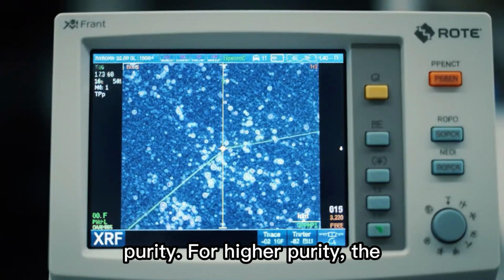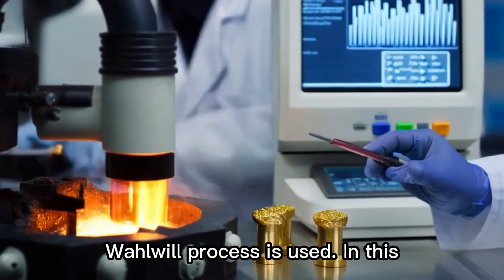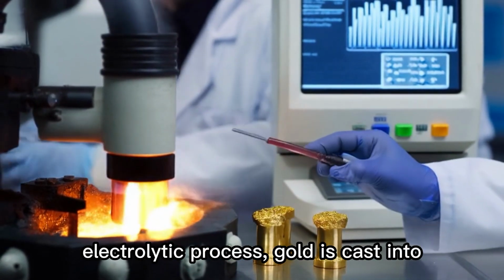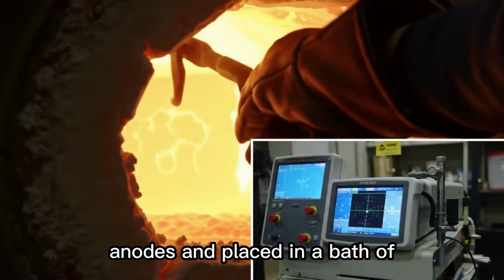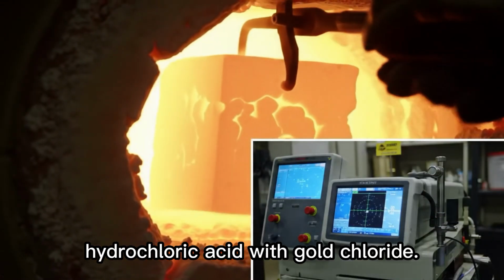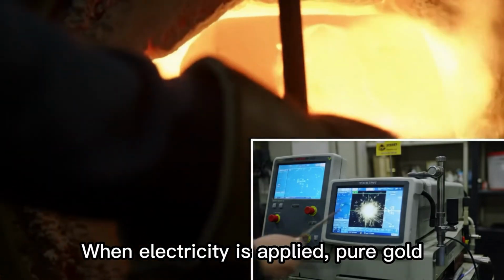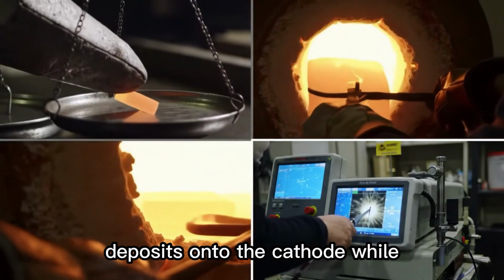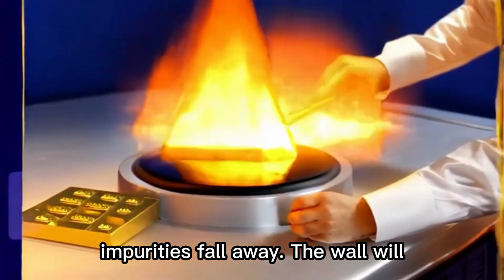For higher purity, the Wohlwill process is used. In this electrolytic process, gold is cast into anodes and placed in a bath of hydrochloric acid with gold chloride. When electricity is applied, pure gold deposits onto the cathode while impurities fall away. The Wohlwill process yields gold that is 99.99% pure or higher.